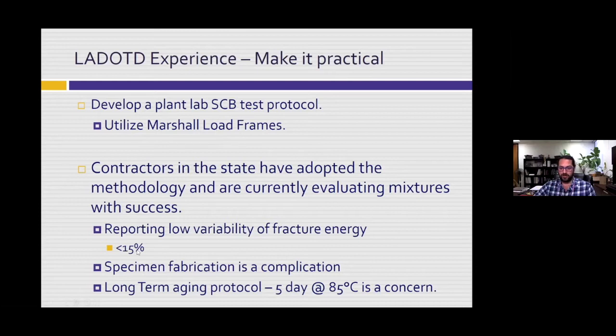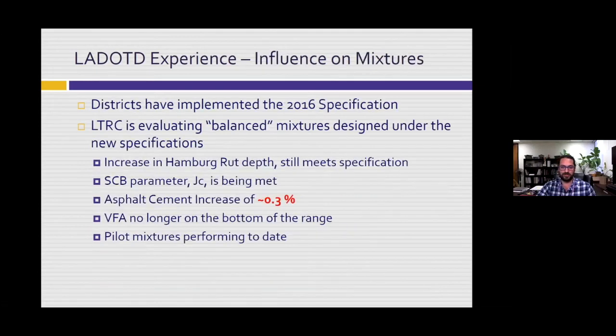And we're seeing reports of the fracture energy, which is the tested value that comes out of the SCB, variability less than 15%, which is generally pretty good for asphalt mixtures. Specimen fabrication is always the hardest part. That's going to lead to the most variability when we do it. And I think the biggest complaint, and one we've heard for a while, and we're still in the process of, is figuring out how to get rid of that 5-day 85C, but still make sure our test is determining the fracture resistance of the asphalt in its most embrittled state, which is its highly oxidized state.